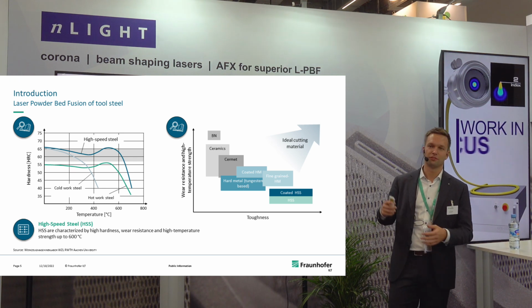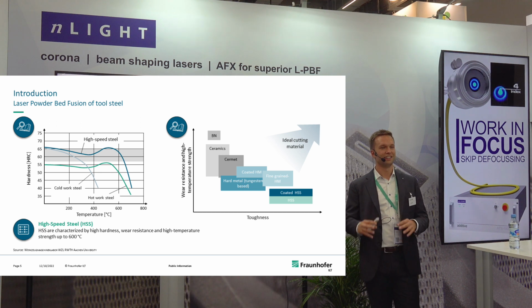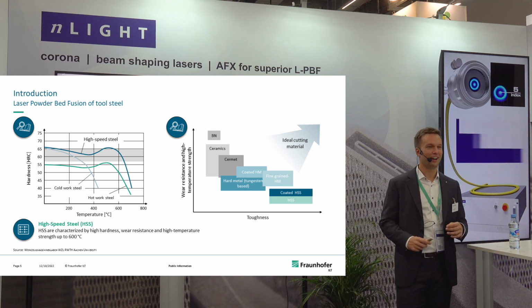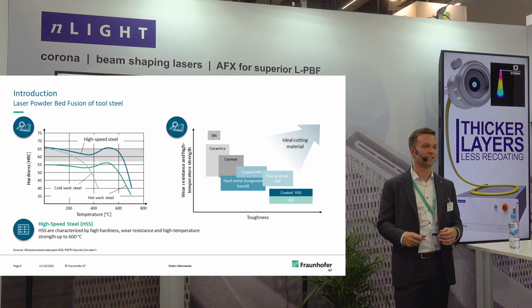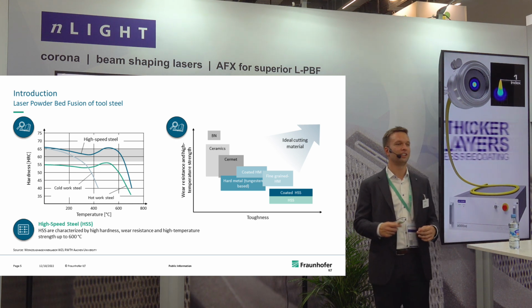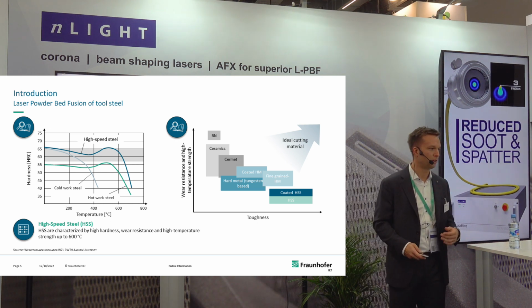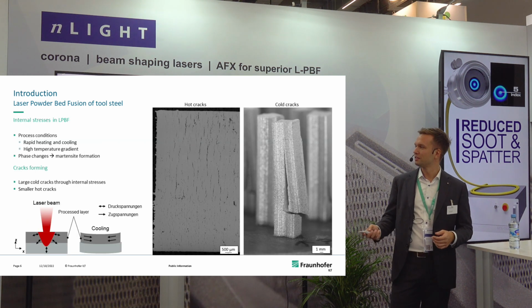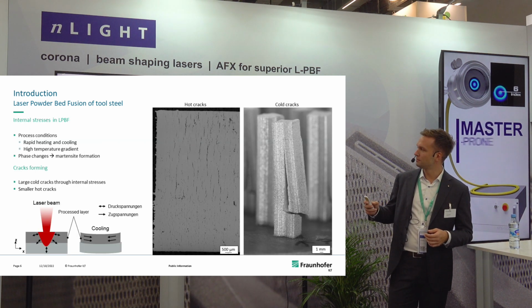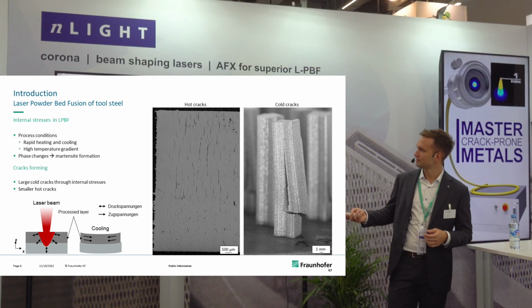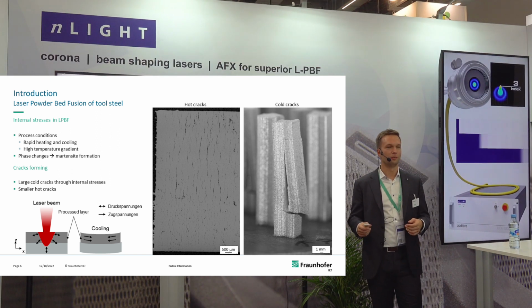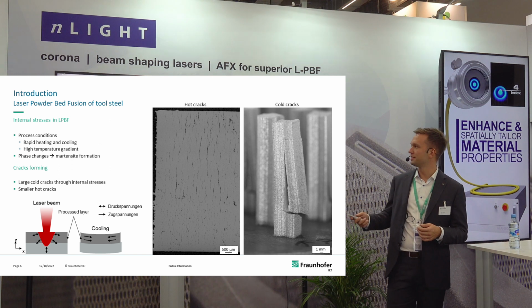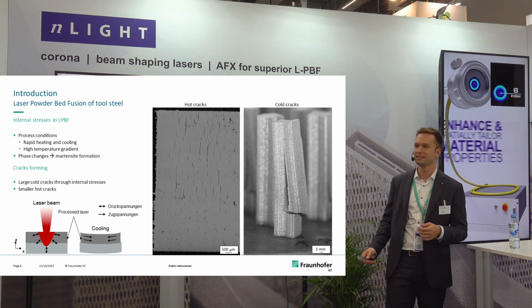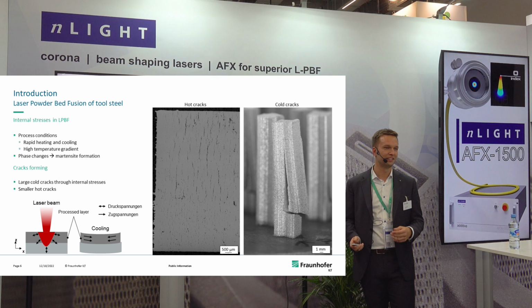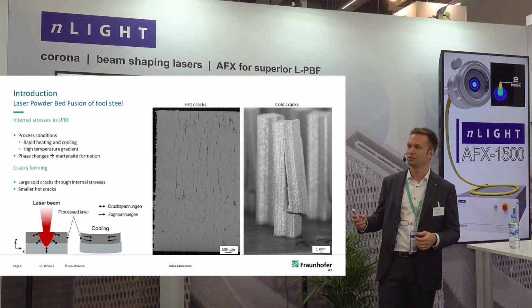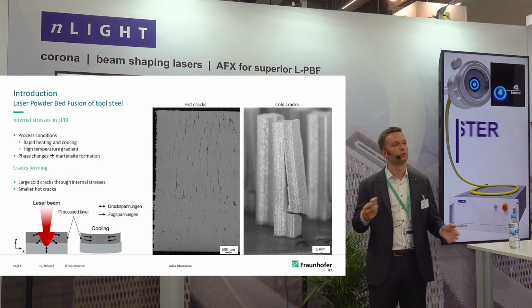But in terms of L-PBF processing, a nightmare. High carbon content is usually classified as non-weldable, so very challenging to process via powder bed fusion. And that's what we are aiming for. So when you look at cut sections from these steels or even entire parts, depending on the process parameters, the geometry, you can end up with one of two things.